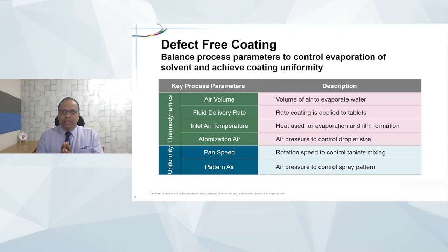So when we look at defect-free coating, from a process parameter perspective it is about balancing the process parameters to control the evaporation of the solvent and achieve coating uniformity. So we're really simplifying and breaking this down into two processes. One is the thermodynamics of the coating process, that is the amount of air, the temperature at which the air is coming, the application of the spray rate, as well as the drying of the coating process. So the overall thermodynamics depends upon the airflow, that is the CFM, the spray rate, the inlet temperature, and to some extent atomization air, because it controls the droplet size and therefore the evaporation rate in the coating process. And then we will quickly look at the overall uniformity of application of the coating.